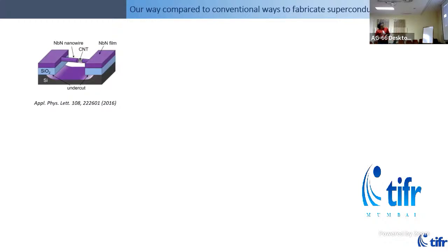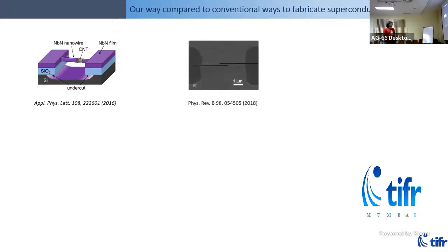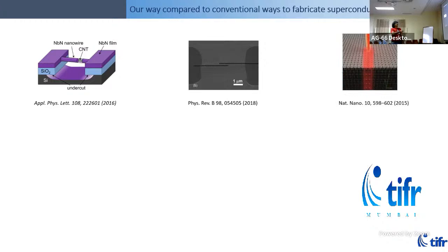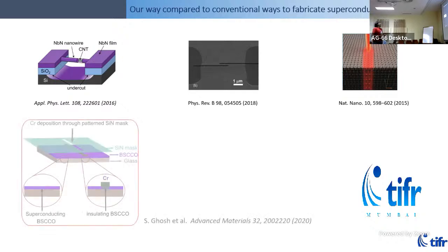So there are a lot of different ways of making superconducting nanowires, which is essentially a narrow bridge of superconductor, which becomes sensitive to external radiation. People use wires as a backbone and then deposit superconductor or carbon nanotubes, or use FIB or helium ion based patterning. And the reason why people do all of these is because lithographic processes, the kind of processes that I described to pattern graphene, you can't use with BSCCO for repeatable results because the processing itself degrades the material.